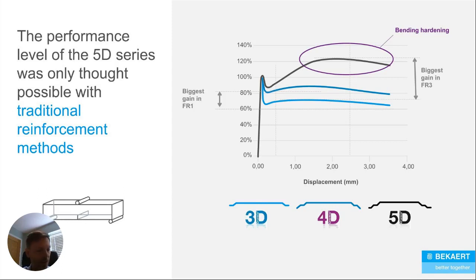Dramix 5D, on the other hand, works differently. Again, the same principle remains. The first crack strength is not increased, but what you will get after that first crack is an increase in the capacity of the concrete. So what we're getting is bending hardening. This is the ability of the concrete to be stronger after it's cracked.